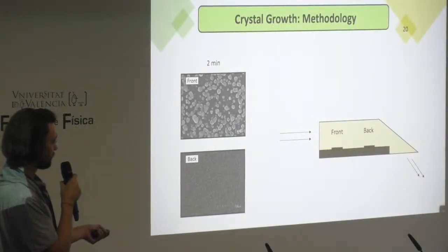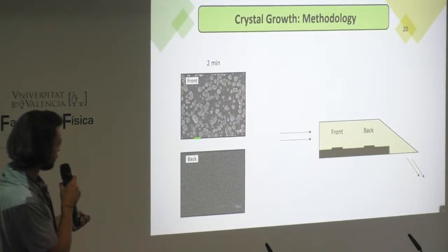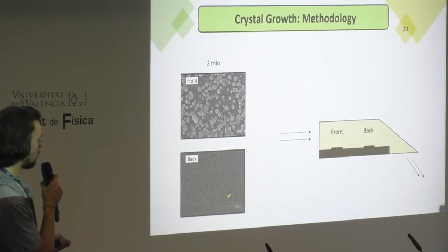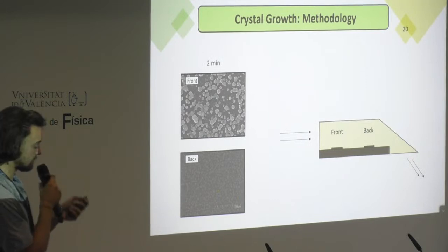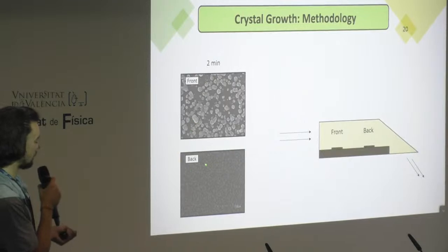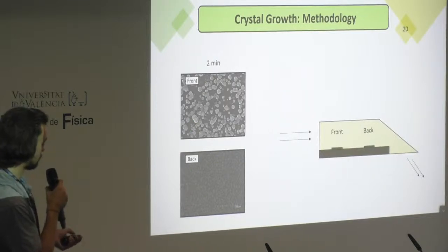So, the hydrodynamic conditions here are very different from here. In the same experiment, for a 2-minute growth, we got this in the front position and this in the back position. And we did the optical measurements, and these particles are too small for exciting the plasmon. So we kept on studying this, but we never stopped doing growths in this position.